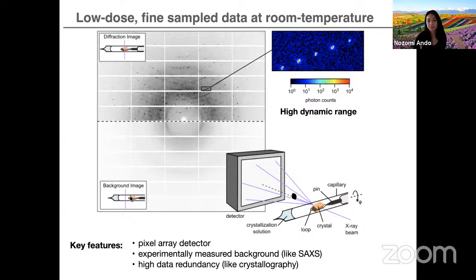So this is a lot of work that's summarized in a single slide. But ultimately, we decided that we needed to have certain key elements to get high data quality. One was to do the measurement as if it was a SAXS experiment, a small angle X-ray scattering experiment. So we would experimentally measure the background as well as the crystal diffraction.